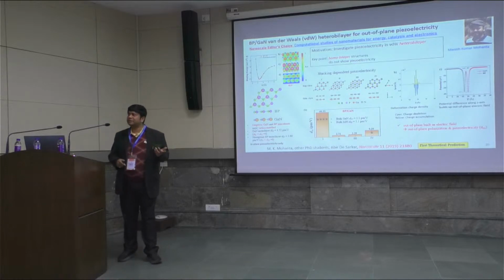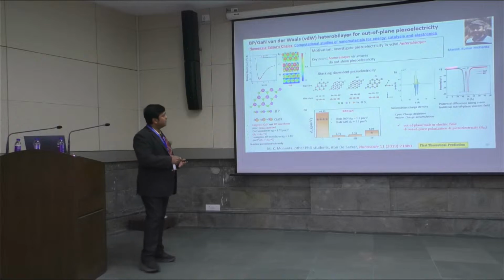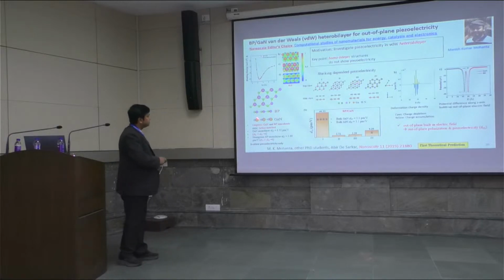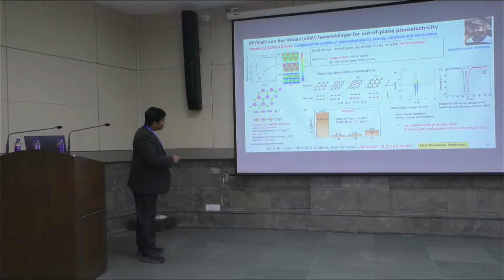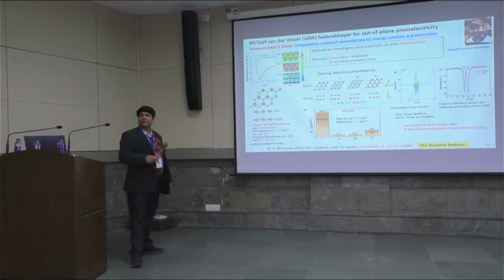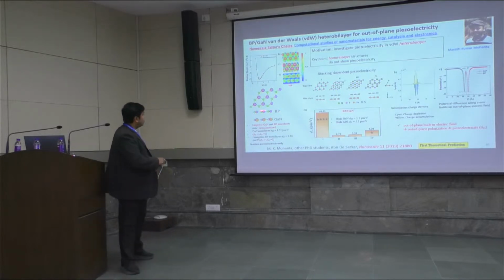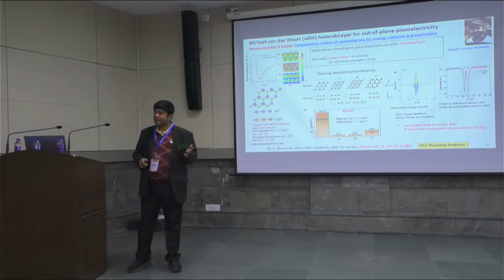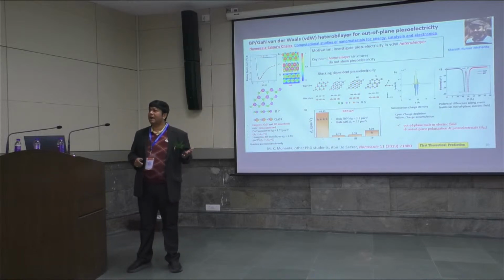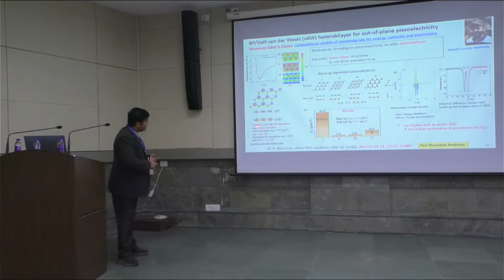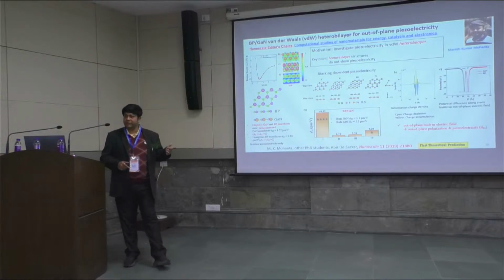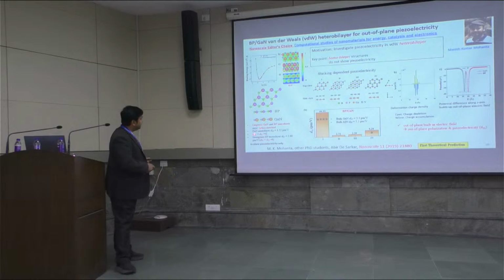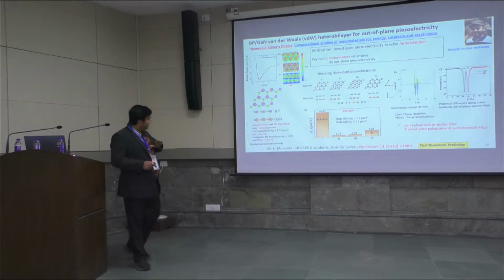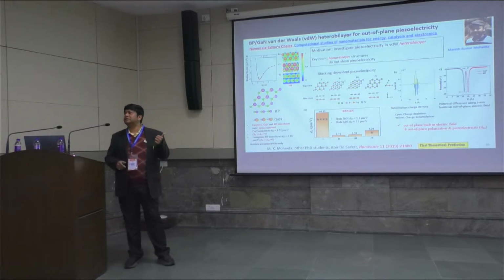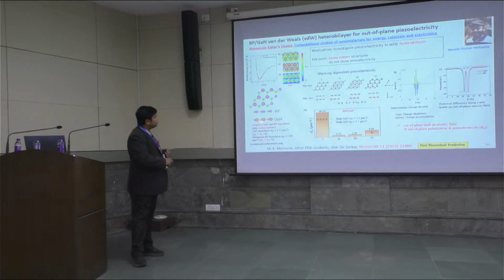And we have evidence to substantiate the claim, and kindly bear with me, I'll show the evidence in the next few slides. So what Manish did is that he designed this van der Waals heterobilayer consisting of a single layer of boron monophosphide stacked on top of a gallium nitride monolayer. These monolayers are very close in lattice constant, and therefore computationally it is not demanding. And experimentally these graphitic nanosheets also exist, so it is of experimental relevance. Now these individual monolayers only show in-plane piezoelectricity, they do not show any out-of-plane piezoelectricity until one is stacked on top of the other.